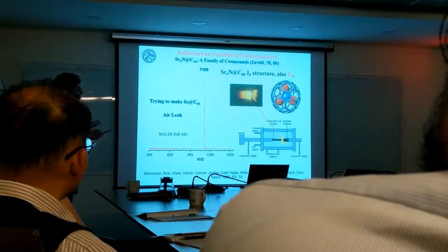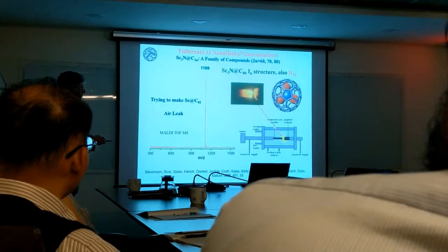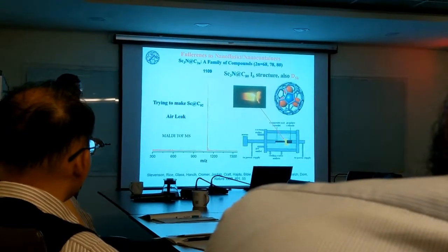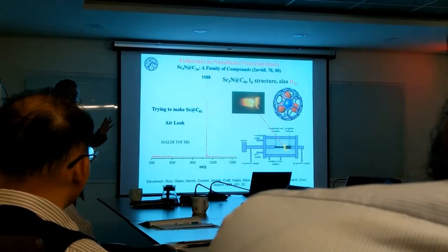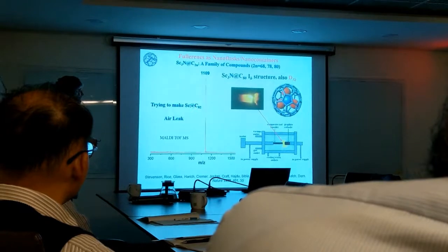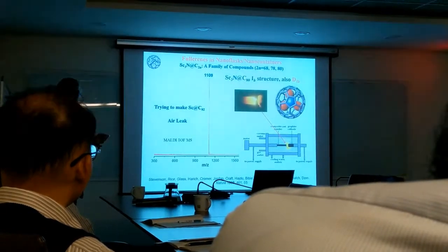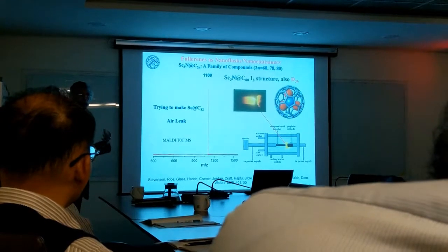So they were actually trying to prepare inside an arc reactor. This is a typical arc reactor with 2 graphite electrodes. One electrode contains a hole, and in the hole they had scandium oxide. Okay? And they were trying to prepare scandium inside. This symbol, the at sign, means inside, the C82. That's what they were looking for. But they didn't find it.